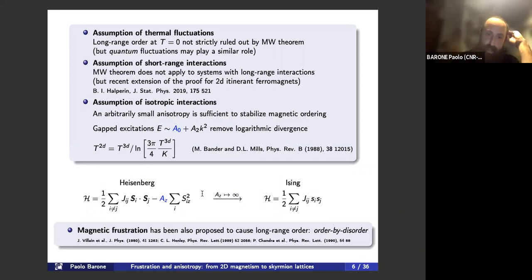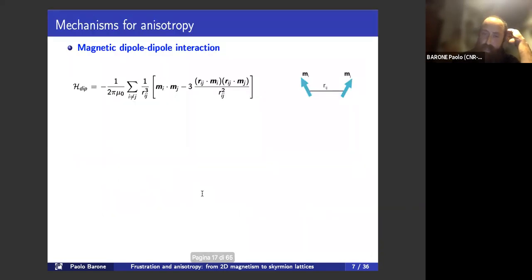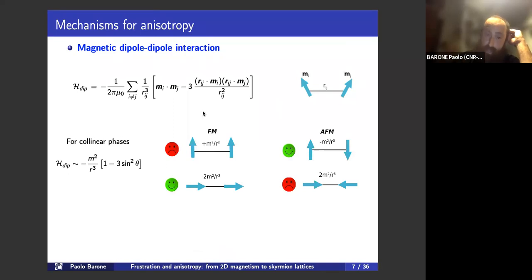Now, having understood that the isotropy assumption is the most important one, we can wonder which are the mechanisms responsible for anisotropy. And the most ubiquitous one, we have already seen also in the previous talk, is the dipole-dipole interaction. This, of course, depends on the relative orientation of the spins. It can be immediately seen if we consider a collinear phase, and we take as the magnetization axis the bonding vector axis between the two magnetic moments. And of course, this interaction selects a specific direction for the magnetization, which depends on the relative orientation of the magnetic moments, as it's seen here for the ferromagnetic and antiferromagnetic cases.